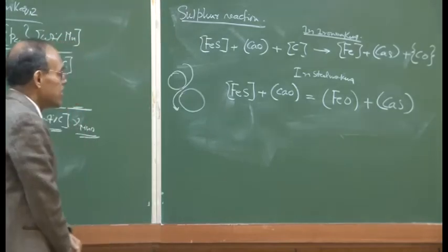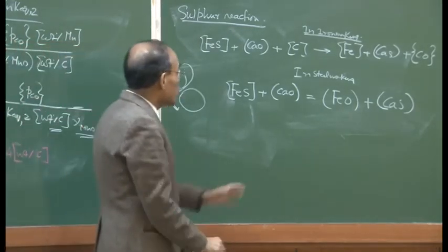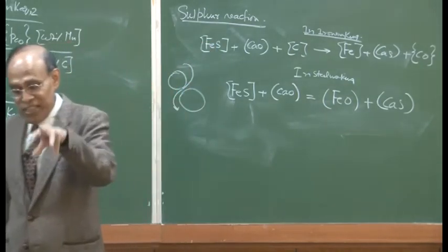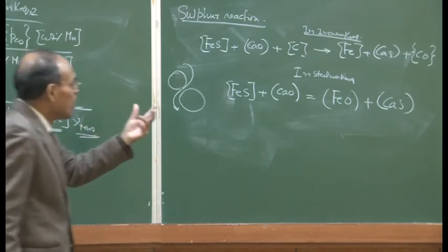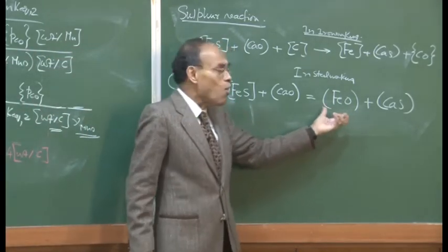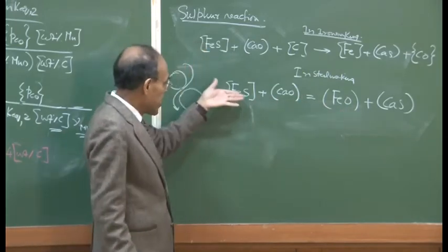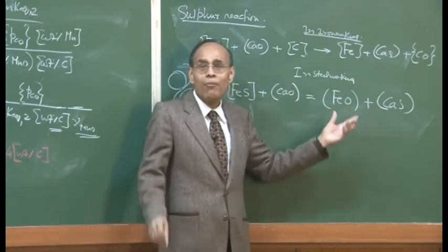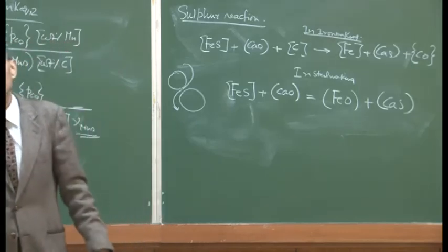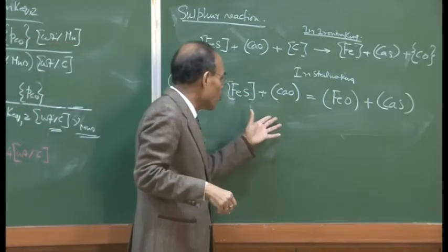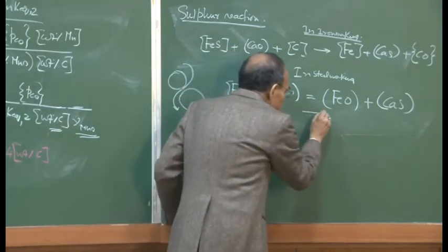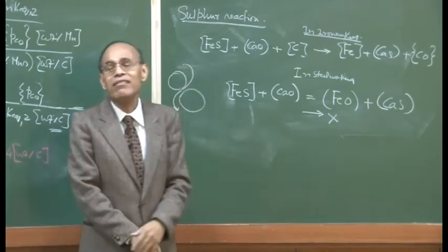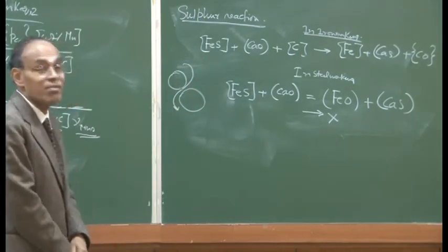It is again a slag-metal reaction, and we must see that, because of oxidation and oxygen injection, FeO is forming. So the activity of FeO in the slag is very, very large. Further oxidation in steel making drives this reaction from left to right, resulting in the formation of FeO, but FeO is already formed or forming because of the oxygen injection into the bath itself. Therefore, the likelihood of this reaction proceeding in the forward direction under steel making conditions is going to be extremely remote.